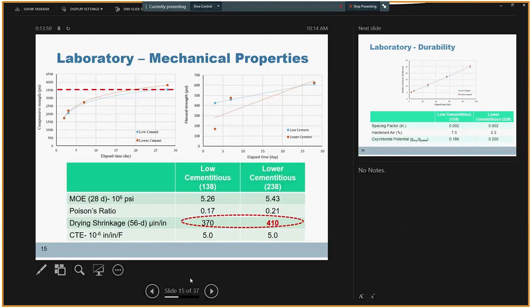And the interesting thing here was the higher drying shrinkage value observed at 56 days for the concrete with lower cementitious material. Well, we are reducing the binder content and we are expecting lower drying shrinkage.